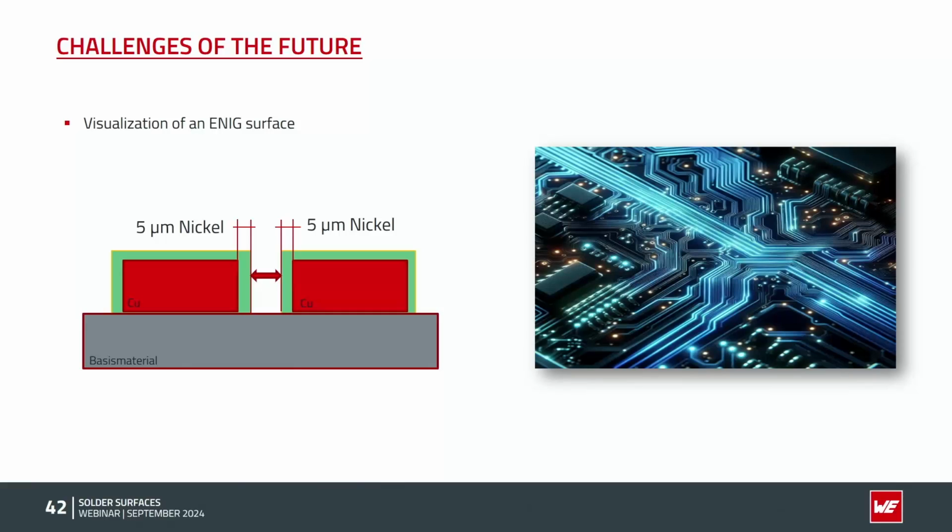If we look at 2 adjacent pads in this cross-sectional picture, we can see that the spacing between the 2 pads is reduced by about 10 micron, which hurts a lot if you want to have a very high density design.